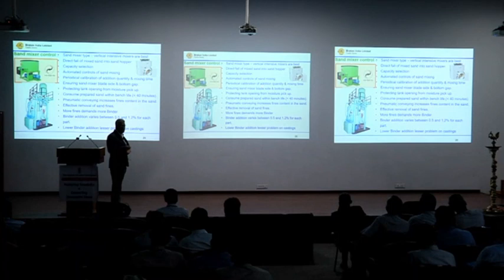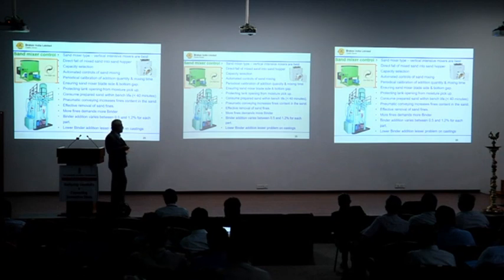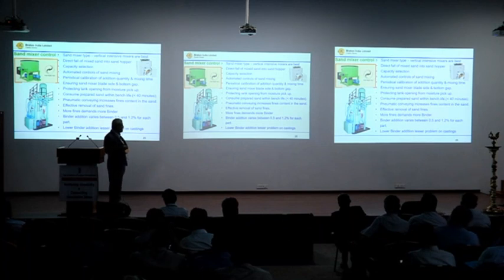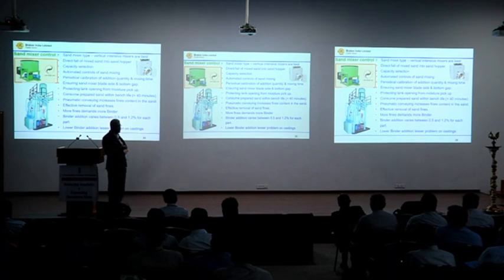Automated controls on sand mixing time and resin additions. Periodical calibration of addition quantity and mixing time must also be done. Ensure sand mixer blades have proper side and bottom gap; if these gaps are not maintained, the mixing will not be uniform.